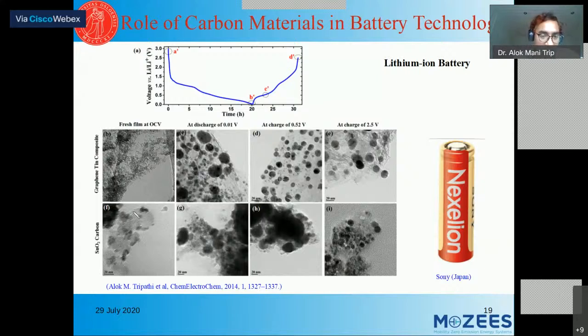But with the spherical carbon, as I showed in my previous slide, the particles expanded in very different ways. Some particles remain crystalline, and some go into the amorphous phase. If it is amorphous, it doesn't react with the lithium. If it is crystalline and a bigger size, it reacts.